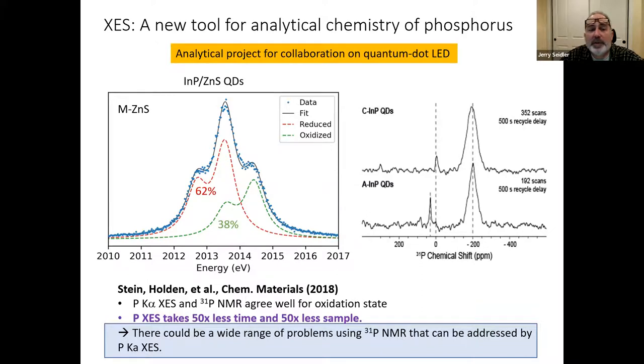And it works wonderfully. This was one of our earlier application papers. This is the phosphorus K alpha for indium phosphide quantum dots with zinc sulfide cladding. And you can see that we infer by comparison to reference standards that it's about 38% oxidized and 62% reduced. And that agreed well with the NMR, except the XES took 50 times less time and 50 times less sample to come to a very similar conclusion. And so that told us there could be a wide range of problems. Right now, they're using 31 phosphorus NMR that could instead be addressed by phosphorus K-alpha XES. This was a quantum dot LED project.